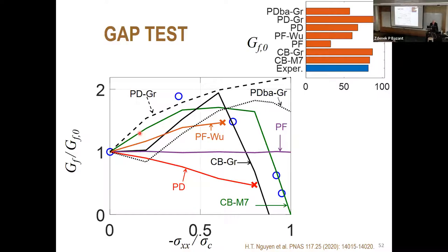Now, finally, the gap test. So I showed only comparison to crack band model with M7. Now, this is compared to other models, again normalized fracture energy versus axial compression from non-compression. This is compression strength limit. So you see that PF-Wu gives insufficient increase and then it fails. It should not fail. Peridynamics goes the wrong way, opposite, and it fails before the end. Bond associated peridynamics goes down and up. It's not really satisfactory.